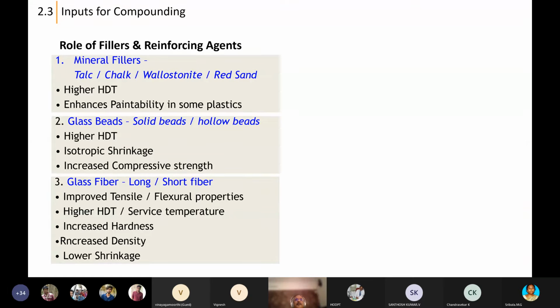Whereas for the same 30% glass fiber, the heat distortion temperature will be close to its melting point. In the case of nylon 66, which is 265, it is very easy to see an HDT of 245 or 250. You will not see the denting. Service temperature is continuous exposure. HDT is applied where momentary exposure to heat is discussed.